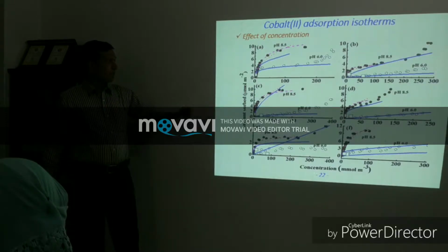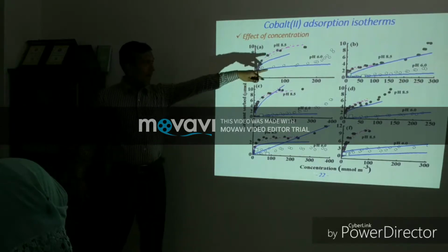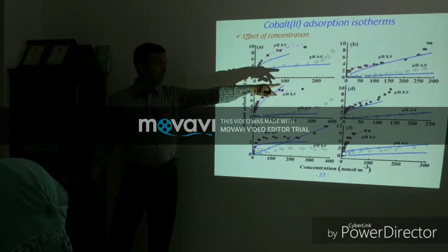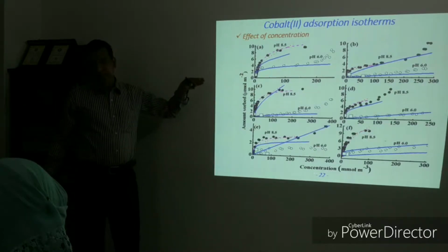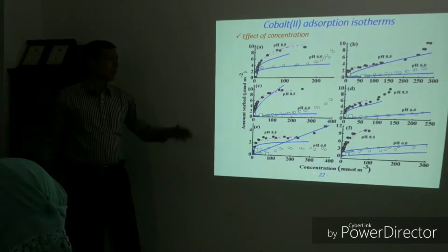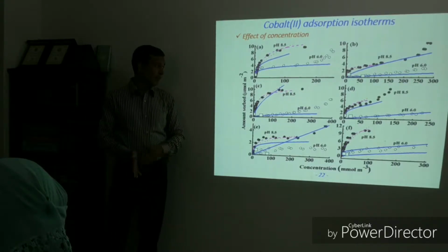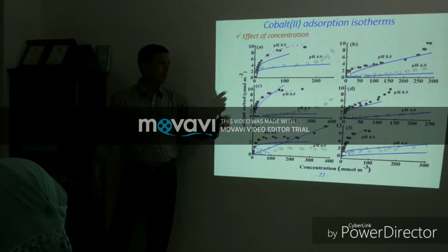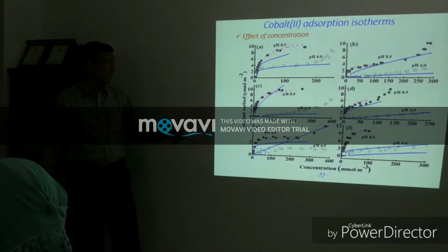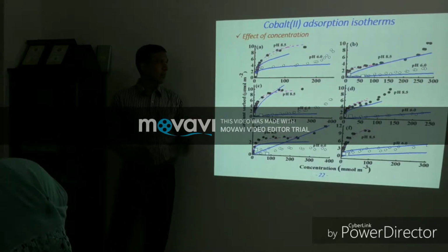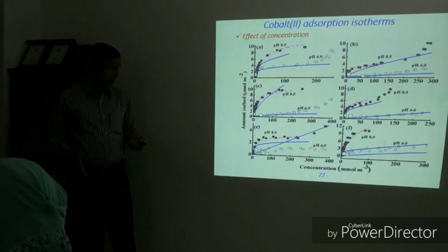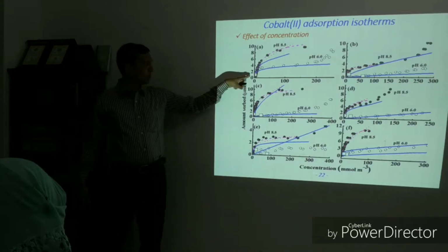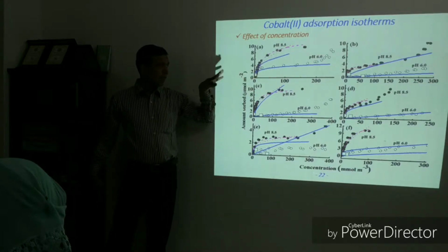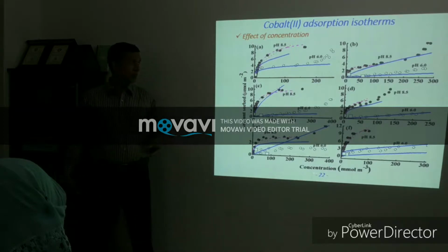On the other hand, in case of pyrolusite and other surfaces at pH 8.5, adsorption reached a saturation point, then further adsorption occurred, which indicates bulk surface precipitation. This straight line indicates the surface complexation modeling, which I will explain later, and this dotted line indicates Langmuir and Freundlich modeling. And to compare our results, we have also put our adsorption-based results, which are indicated by this. It is in agreement with our adsorption-based results.